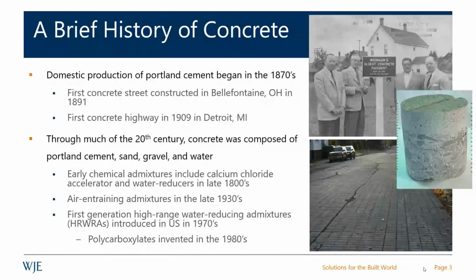And then really we started seeing a revolution in the 70s with the introduction of high range water reducing admixtures that all of a sudden allowed us to significantly reduce our water, which meant we could significantly reduce our water cement ratio to create much more durable concrete, or create concrete with really high slumps at relatively low water cement ratios. This allows us to pump the concrete and do things that we could not do before, even self-consolidating. Polycarboxylates, which are pretty significant, were invented in the 80s, but really started coming on strong in the 90s. And today, most of our higher end, high range water reducing admixtures are based on polycarboxylates.